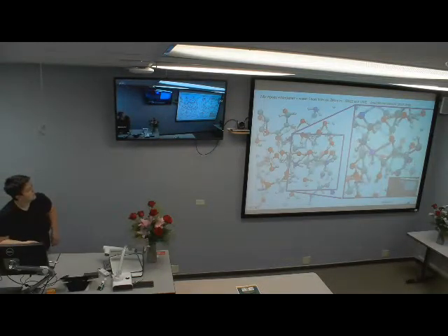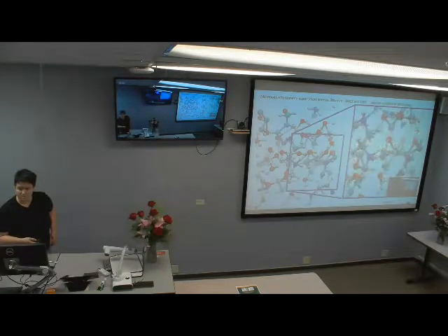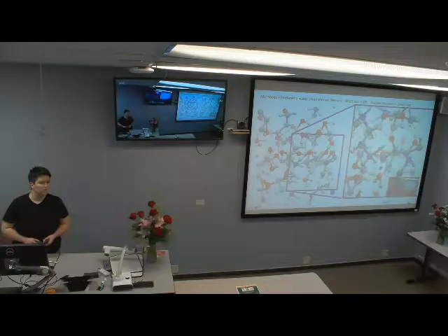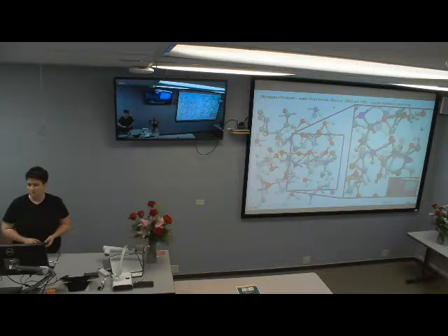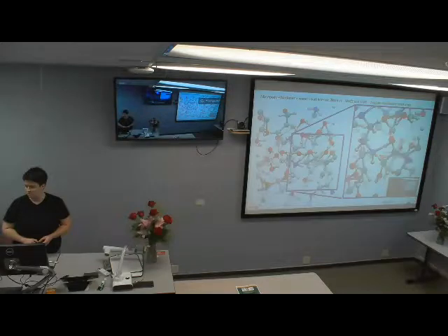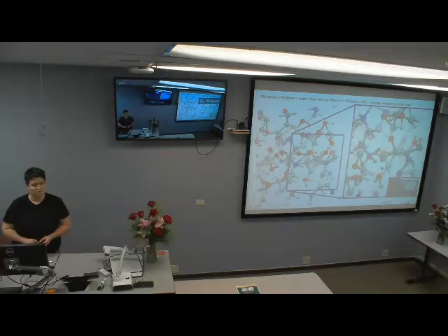Why is it breaking? Heat. Would it break without water? The reaction can occur by itself. The amine acts as a nucleophile and attacks the epoxy ring. Have you done these calculations without water, just in vacuum as well? No. Just with water. But I think the question is, if you don't have water, would this breaking of the bond happen in your simulation cell? Yes, it can. You can just mix the 2 components. I mean, in experimental conditions, it happens without water, but you didn't really check.